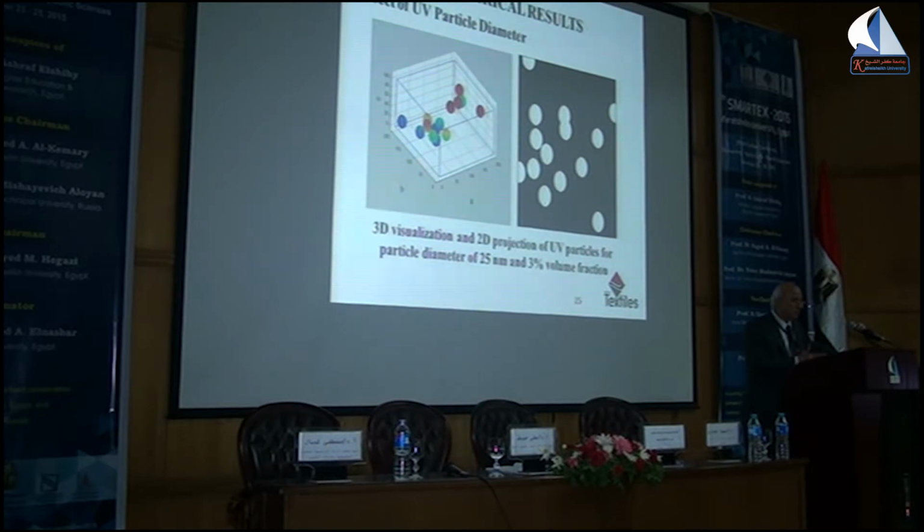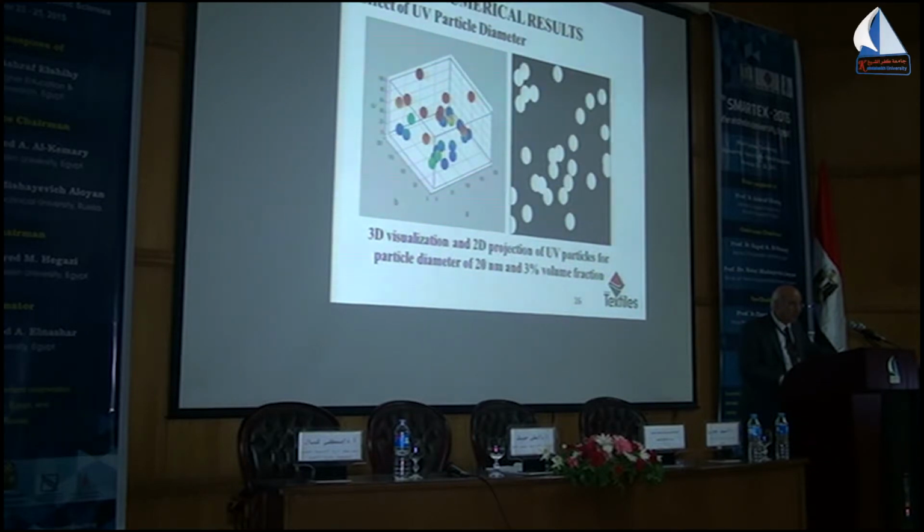This is the effect of UV particle diameter. If we change the diameter, here is 3D visualization on the left, and this is a projection on the right. And if you look at this here, we have the particle of diameter of 25 nanometer, and we have 3% volume fraction. Then we increase now, same thing, but we play with the diameter.